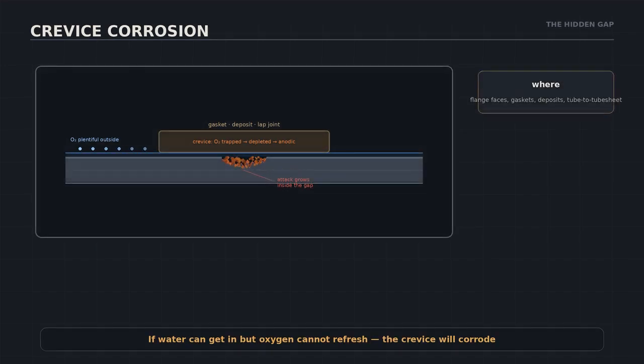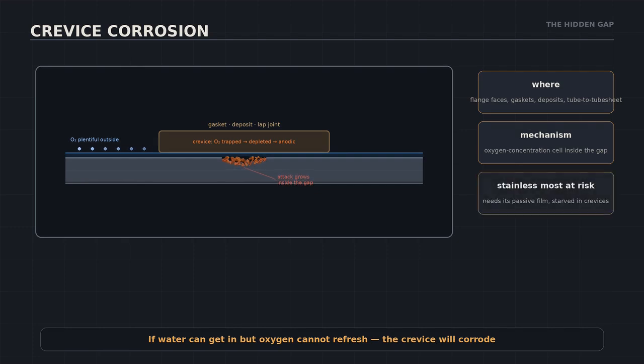Crevice corrosion hides in the gaps, flange faces, gasket edges, under deposits, lap joints, tube-to-tube sheet crevices. Water wicks into the tight gap and gets trapped. The oxygen inside is consumed by corrosion and cannot be replenished, so the crevice becomes anodic to the bold surface outside. Attack grows inside the gap, out of sight. Stainless steels, starved of the oxygen their passive film needs, suffer most. The design fix: eliminate gaps, use full penetration welds, and keep things drained and clean.